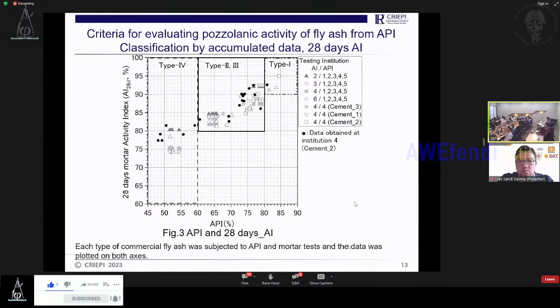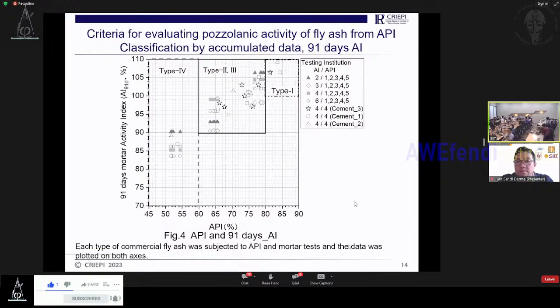For type 1, the lower limit was determined as 80% in API. For type 2 and type 3, we determined the lower limit as 60%. And for type 4, we determined the lower limit as 45%, as shown. The next figure shows the relation between API and the 91-day mortar activity index.